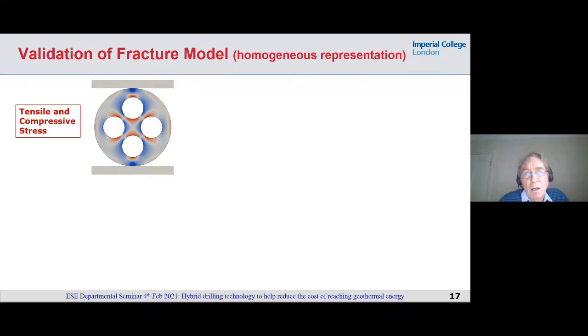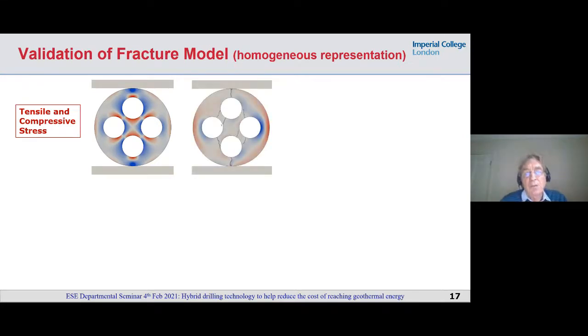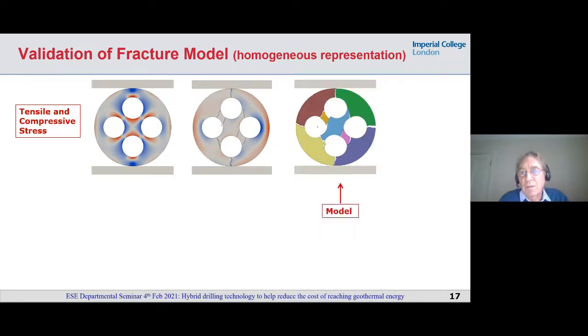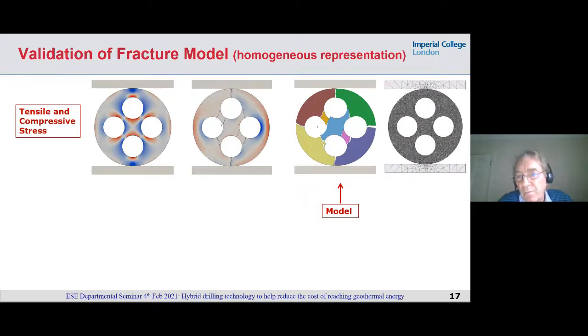And you can see now a little bit later the cracks have developed, and you can see the 2 halves that are still holding it up. On the left and right hand side you can see those red zones. That's the outer arc going into bending and going into tensile stresses. It looks like there's a very high stress gradient there on the right hand side, and of course that's where it's about to break through, and sure enough this is the final model failure pattern. 7 blocks, 7 separate fragments, color coded for reference. And I'll also show you the very fine mesh that Ardo used for this simulation.